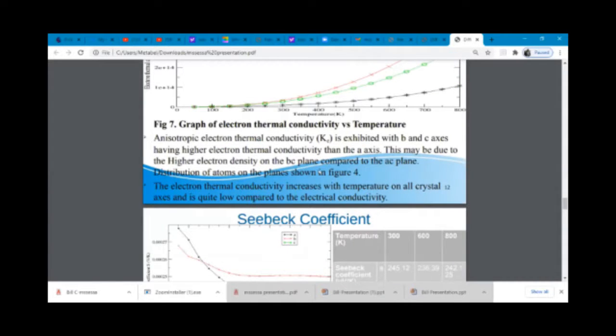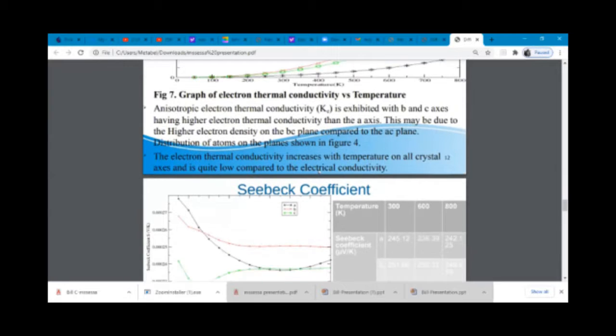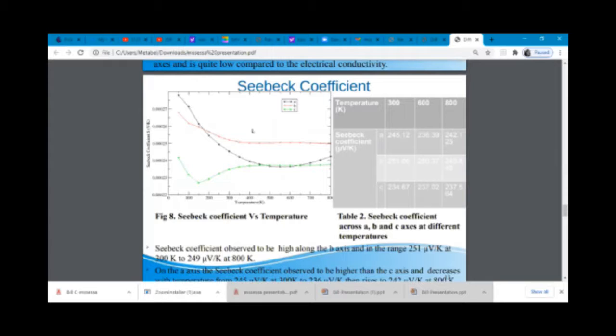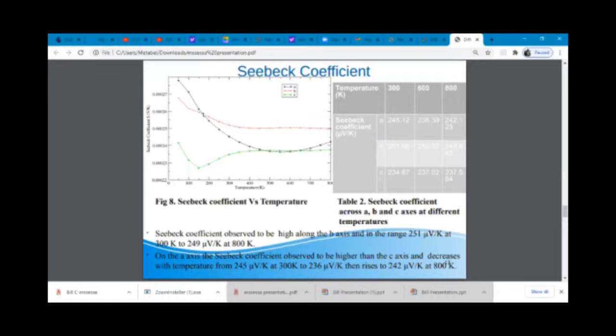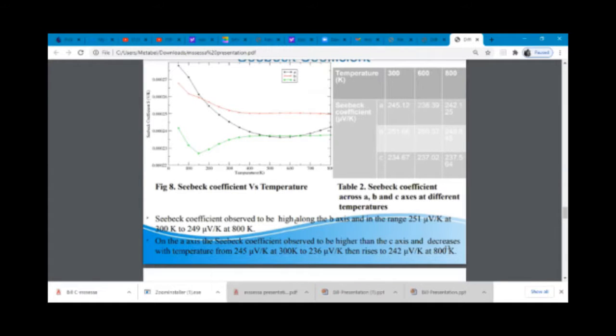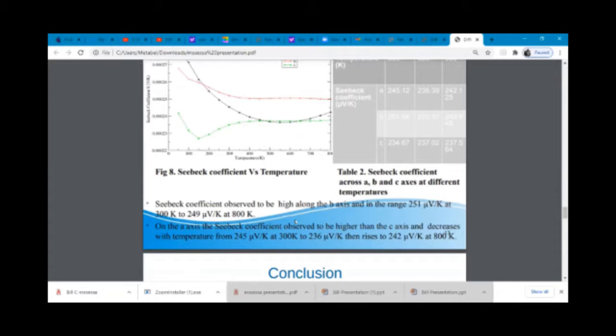I was also able to get the Seebeck coefficient as a function of temperature for the same material. For Seebeck coefficient, the B-axis was found to be having a higher Seebeck coefficient as compared to the other two axes shown in the graph. The red one, that's the B-axis. The Seebeck coefficient was observed in that range, 251 microvolts per Kelvin at 300 Kelvin, and as the temperature increased to 800 K, the Seebeck coefficient was found to be 249 microvolts per Kelvin.